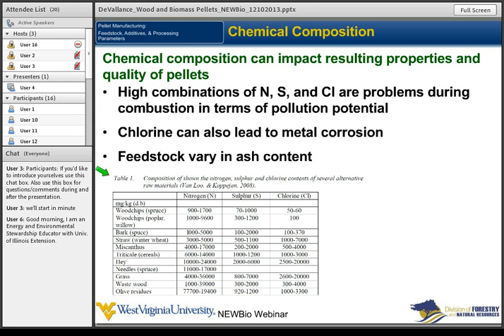Chlorine can also lead to metal corrosion. So this is a property that's looked at pretty closely by the pellet fuel industry. You don't want to start corroding your pellet stoves, things like that. So chlorine is one of the things that's actually measured very frequently and kept to a minimum. And we have different feedstocks that are going to vary in ash content.